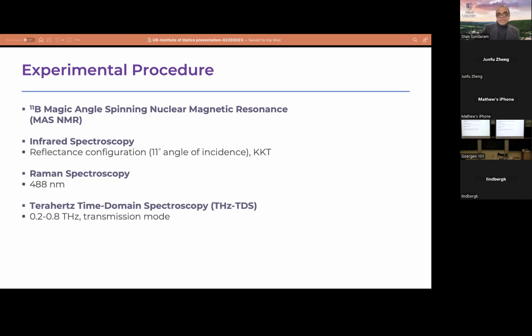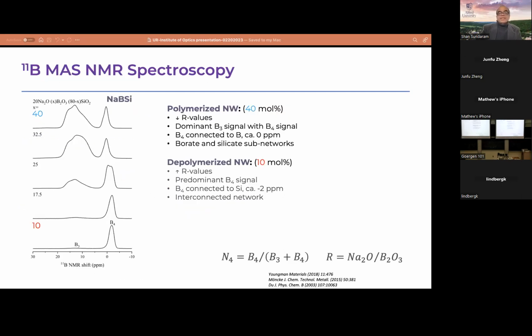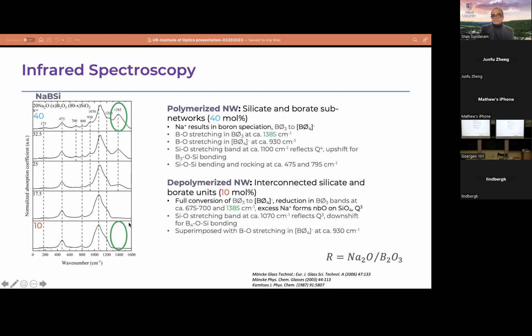So we used 11B magic angle spinning NMR data. We use infrared spectroscopy and Raman spectroscopy to get structural information from the glasses we have made, and then we measure terahertz properties and correlate. We develop this relationship by putting them all together. This is just a sample of our 11B spectroscopy. You can see here, this is 10 mole% of B2O3, and this is 40 mole% of B2O3. You can see a gradual change of spectral features here.